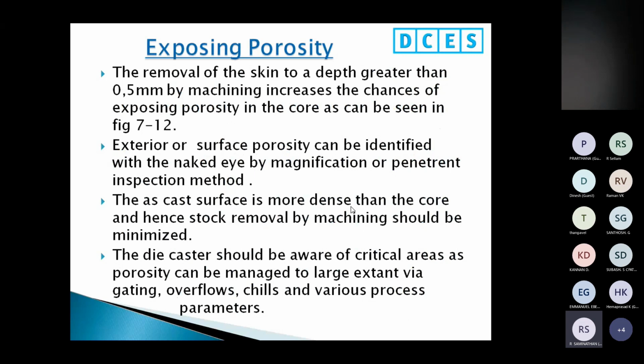Exposing porosity. The removal of the skin to a depth greater than 0.5 mm by machining increases the chances of exposing porosity in the core, as can be seen in figure 712. Exterior or surface porosity can be identified with the naked eye, by magnifying, and by penetrant inspection test. This is usually what we are doing. The as-cast surface is more dense than the core, and hence stock removal by machining should be minimized.